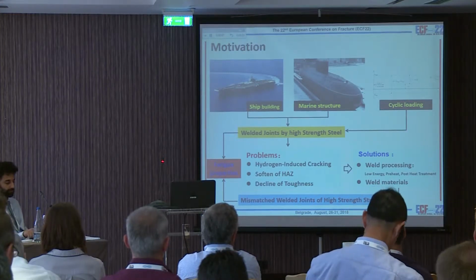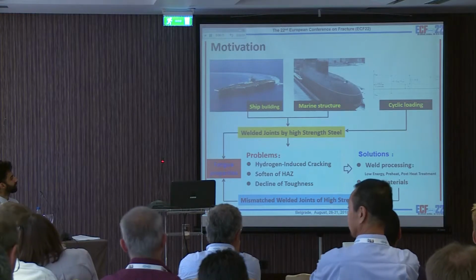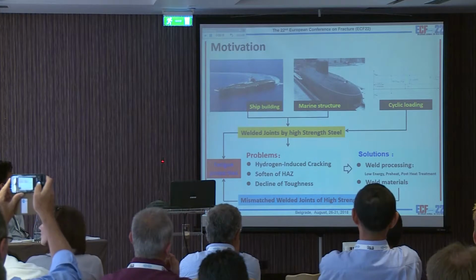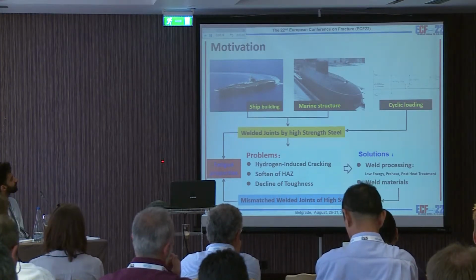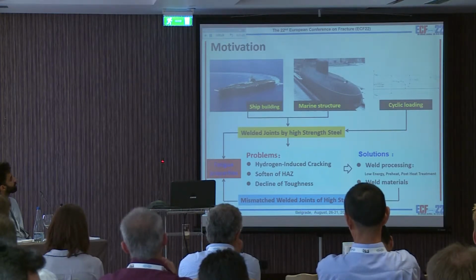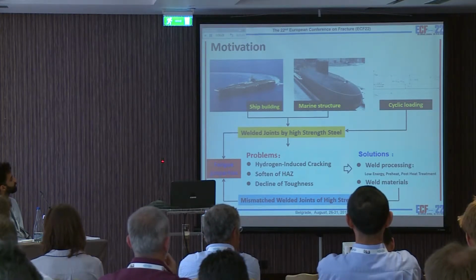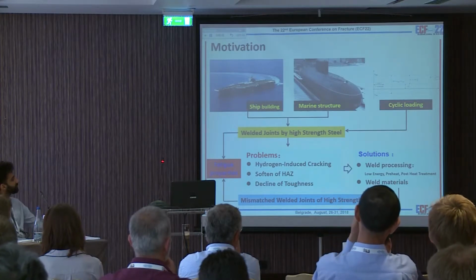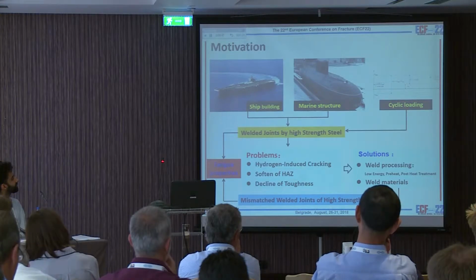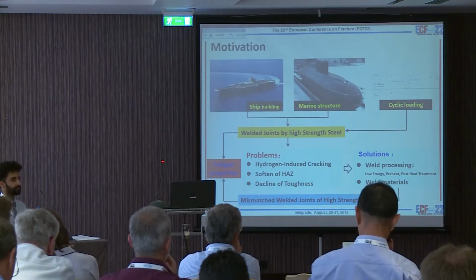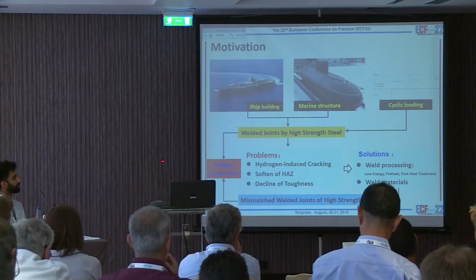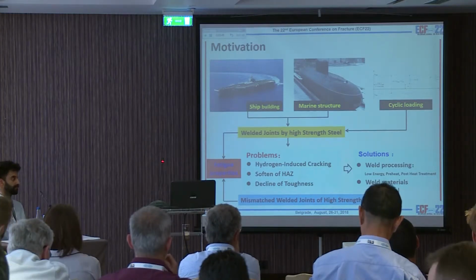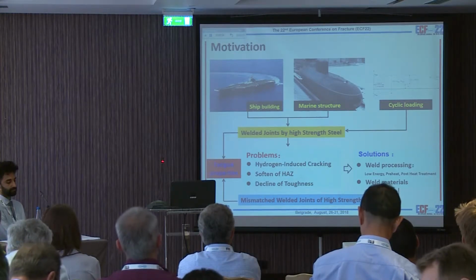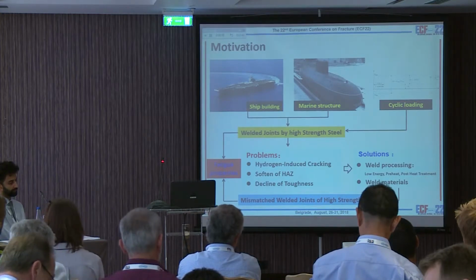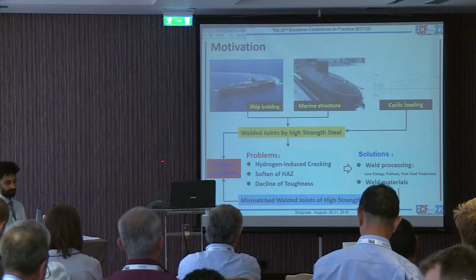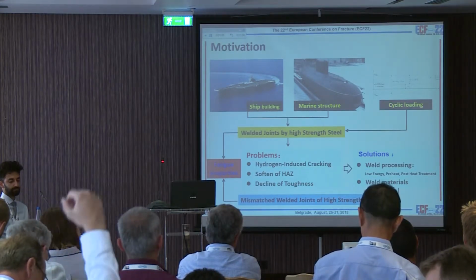Shipbuilding and marine structures are built with high strength steel, even using ultra high strength steel in some crucial components. When the high strength steel is about 800 megapascal, the welded material sometimes doesn't meet the strength need. It can also cause problems such as hydrogen induced cracking, softening of the heat affected zone, or a decline of toughness.